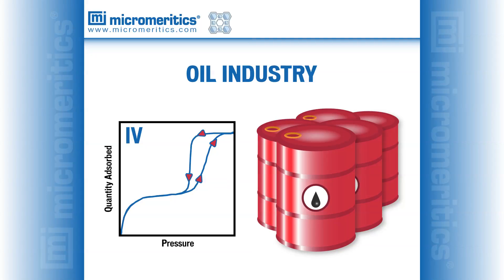They may include a microporous component with pores no larger than 1 nanometer in diameter. In contrast, for processes where deposition of impurities from natural crude oil is required, catalysts with larger pores are employed. This is called a hydro-demetallization process in which larger pores perform better.